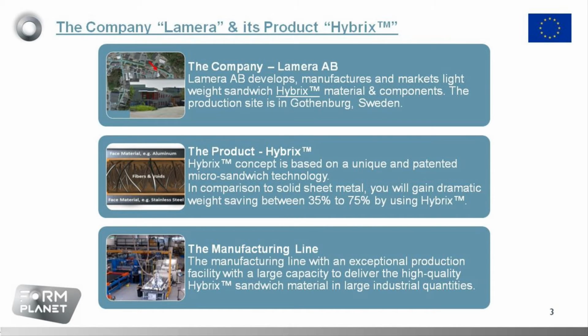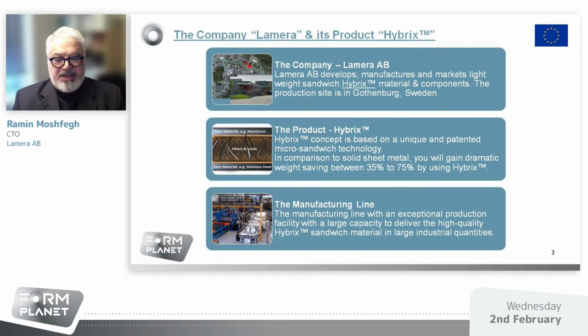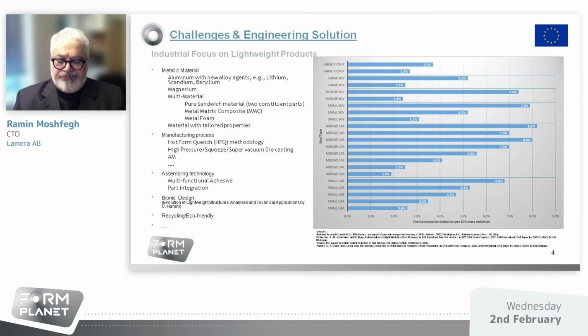If you compare this material with a solid sheet metal, you can actually save weight between 35 to 75% by using Hybrix, and it's highly dependent on which type of component you want and the application area. And the manufacturing line, as I mentioned, has huge capacity and delivers high quality of the material. This is about the company.